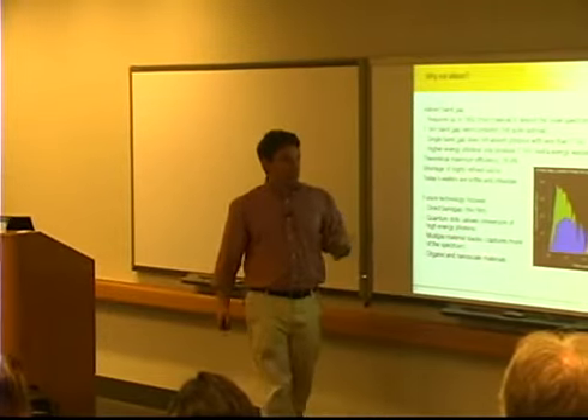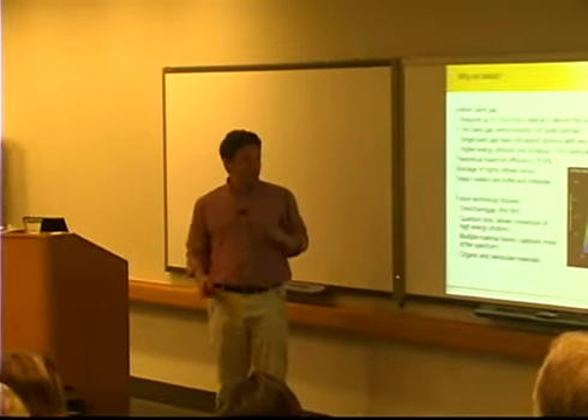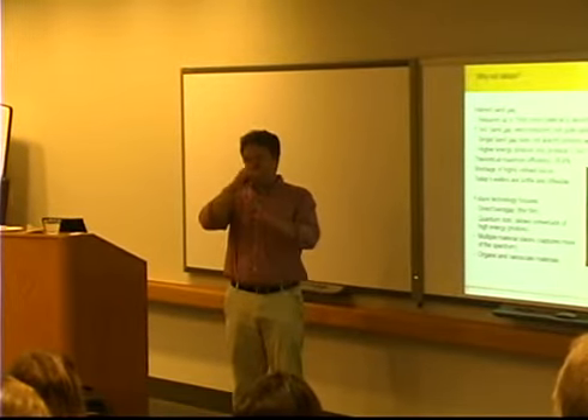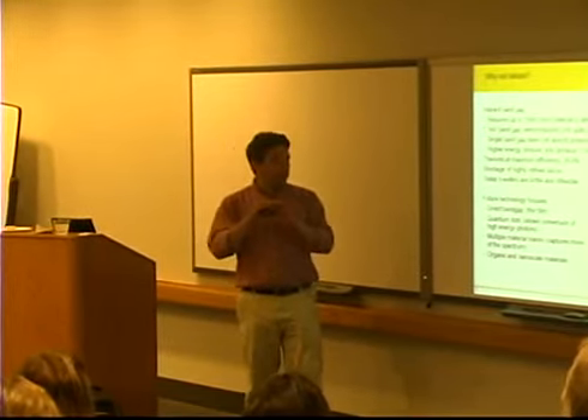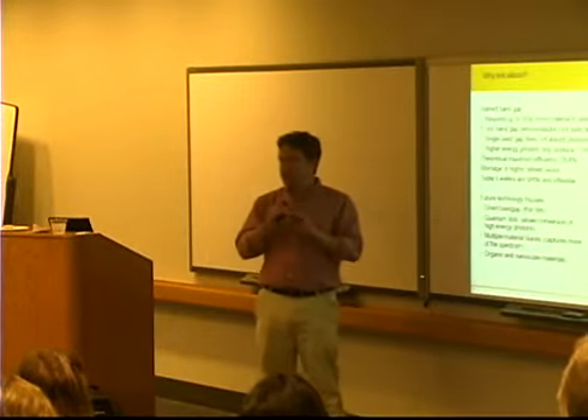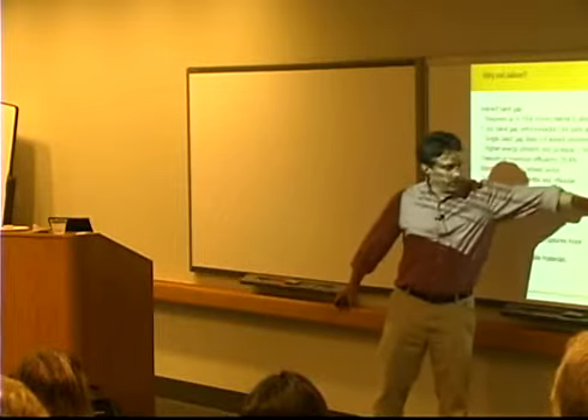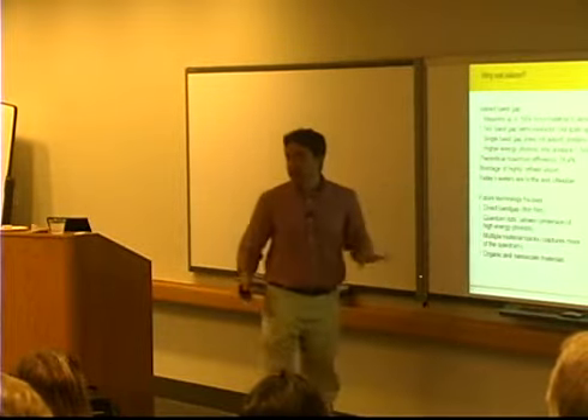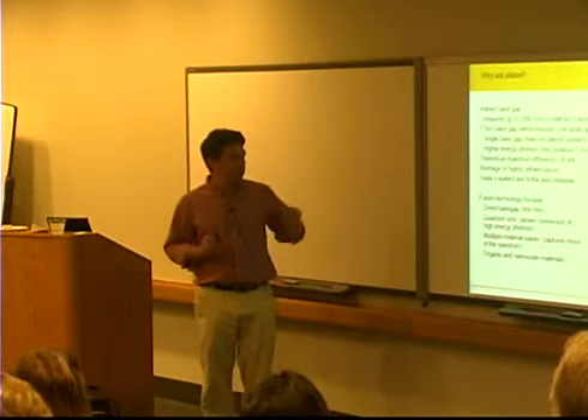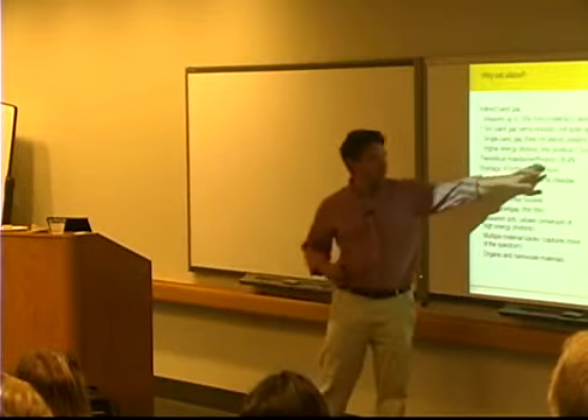Also, we can't get more than 1.1 eV because anything higher than that that's absorbed falls down to the basic 1.1 eV level, and the extra energy is lost in heat. And so all of this up here is also lost, and that's about 30% as well. So our maximum theoretical efficiency for this silicon perfect device would be around 29%, which isn't great.